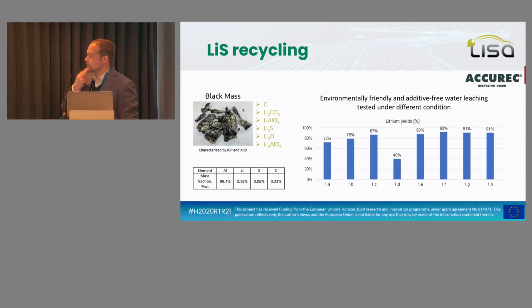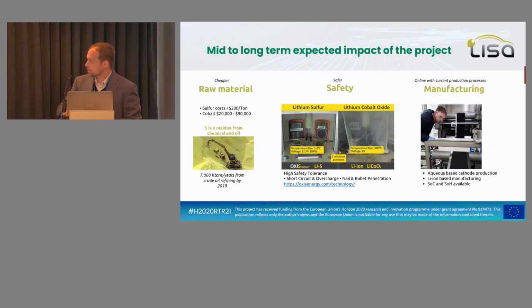We have been working on the recycling. So here this is a water-based recycling. So we can see that depending on the parameters that we apply, we can reach more than 80% of lithium recovery. Basically in the cell you have carbon, sulfur, aluminium, copper, lithium. So the metal of interest is lithium. So this is done also.